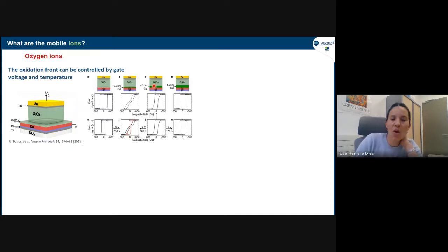So this is one of the pioneering works done in 2015. This is what I showed you before. It's cobalt gadolinium oxide and a top gold electrode. Here, what they showed initially in this top line of hysteresis loops is that if you change the oxidation level at the cobalt interface, so let's say if you on purpose insert a metallic gadolinium layer in between, then you will get this series of different loops.